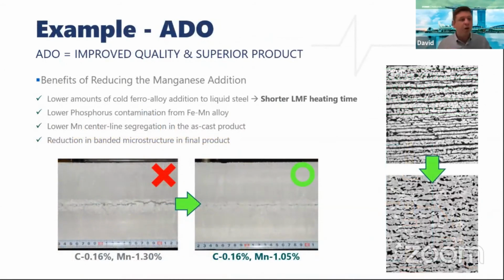This is also not to mention the quality improvement that we had by lower ferroalloys residuals contamination, especially phosphorus from the ferromanganese. The high carbon ferromanganese contains an important amount of phosphorus, and especially the internal quality of this slab due to alloy segregation. There was an important improvement that we see, because I think it's well known that the reduction of the manganese improves the solidification path, so you can have more diffusion during the liquid to solid transformation, leading to less alloy segregation, as you can see.